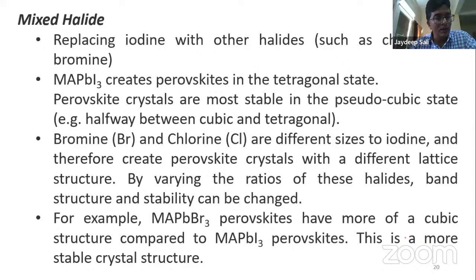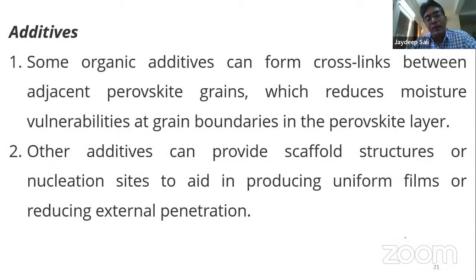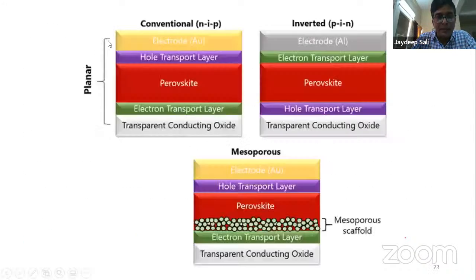So different ways are there to reduce the degradation of the perovskite. One way is to use additives. I mean, use some organic additive during the synthesis of the perovskite thin films, which can form cross-links between the perovskite grains. Now, to explain this, I will go to the diagram directly.